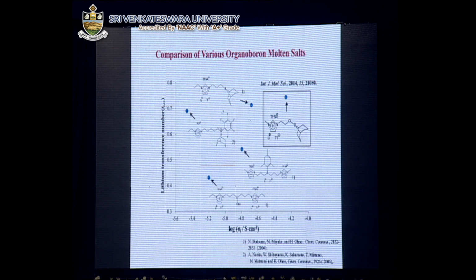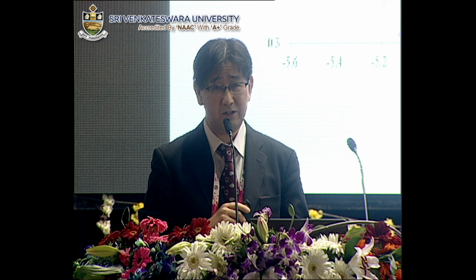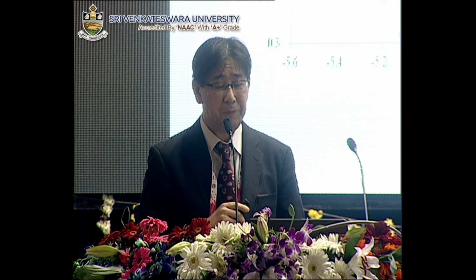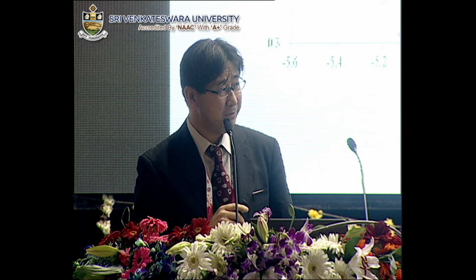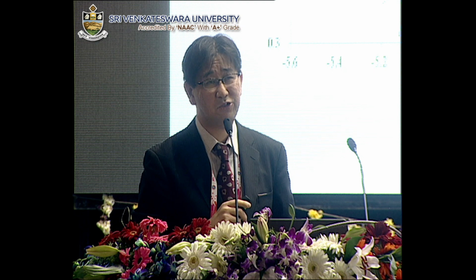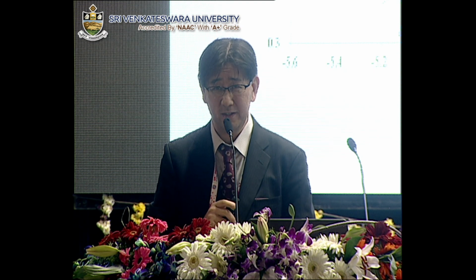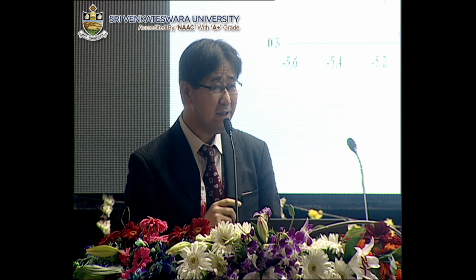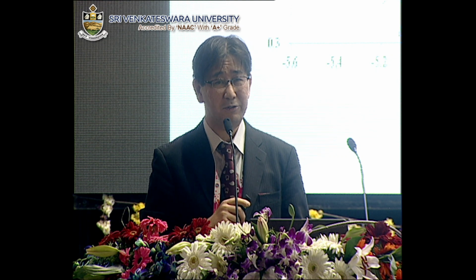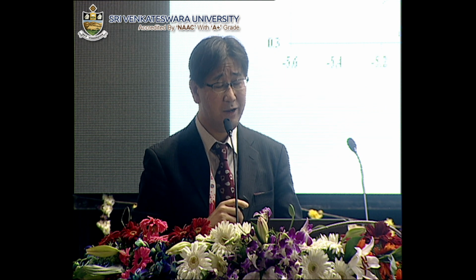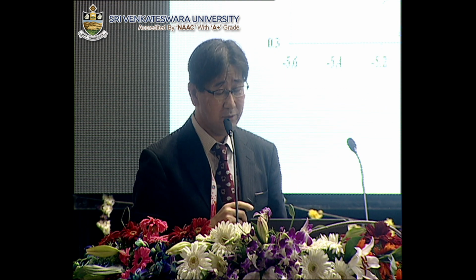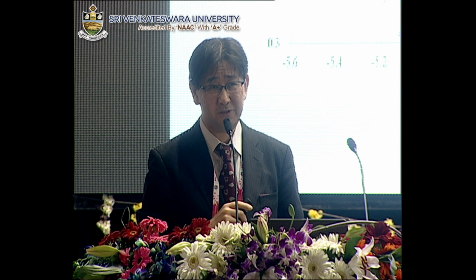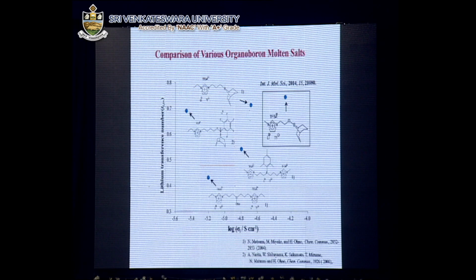To enhance the lithium transference number, we developed various kinds of organoboron ionic liquids, in which the ionic liquid moiety and boron moiety were covalently tethered. And recently we have also developed one organoboron ionic liquid showing relatively high ionic conductivity and high lithium transference number at the same time. But so far we have been working on this kind of approach because for most of the systems, ionic liquid was not miscible with boron compounds.